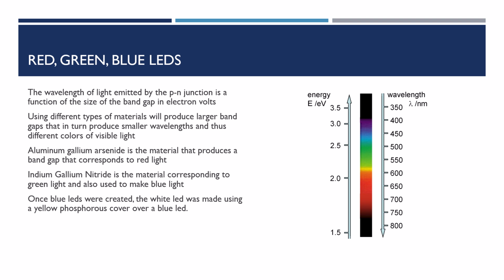Aluminum gallium arsenide was the material that produced the first red LEDs. From this energy chart here, we can clearly see why the red LED was the first to be produced, as it requires a smaller band gap than green or blue. To make green or blue, indium gallium nitride was the material used to make these LEDs. Note that although indium gallium nitride is used for both green and blue LEDs, to make a blue LED, a better quality crystal structure is needed than for a green LED.